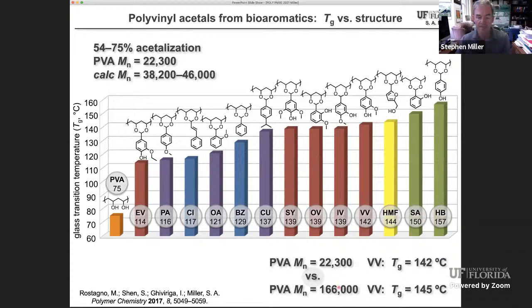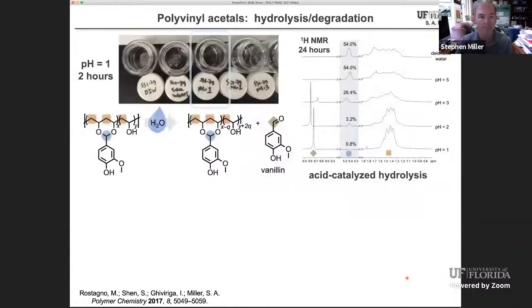We did another test where you can subject this to polyvinyl alcohol, commercial polyvinyl alcohol starting materials of different molecular weights. If you buy a higher molecular weight polyvinyl alcohol, you do see a slightly higher glass transition temperature, but it nonetheless tends to be around this 140 something degree temperature range. So we can throw these at a variety of conditions.